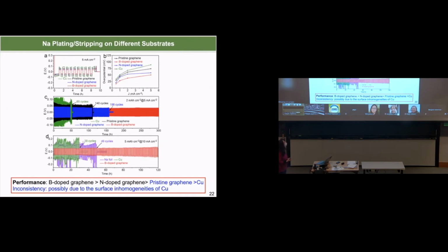Then we tried to see whether our experimental electrochemical performance actually matches the theoretical calculation, to see whether our hypothesis works or not. If you recall, I showed you how to read these graphs. For example, the smaller the voltage range, the lower the voltage hysteresis. But some of you might see a really low polarization here. However, this means that the battery actually had a short circuit. The battery died at this point because of dendrite growth or extra consumption of the electrolyte. So in this case, if we compare the performance, we find some inconsistency between the experimental results and our theoretical calculation.